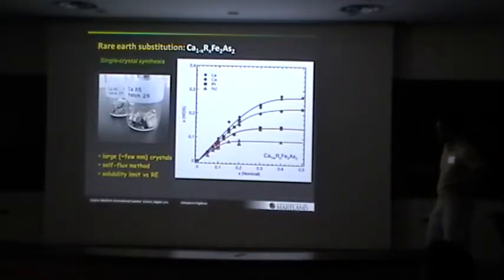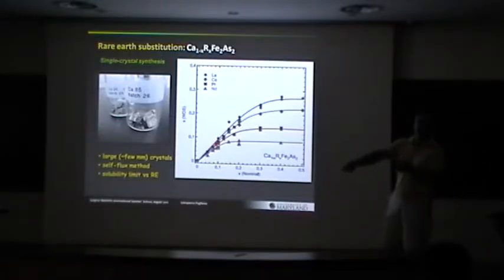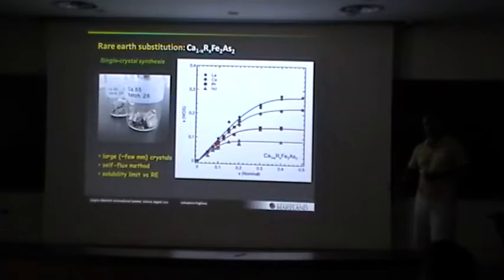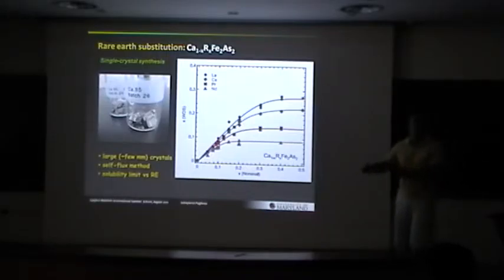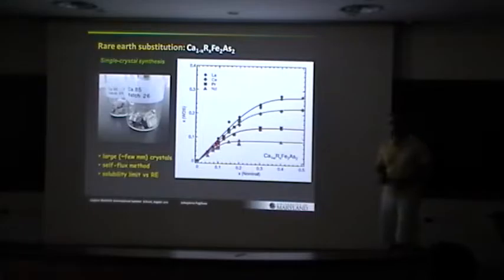This is the concentration of rare earth we start with, and this is what we measure. You can see that for lanthanum, for instance, we get a pretty good linear relationship up to some higher concentration, and we kind of run out of steam, so you can't put more lanthanum in. And then as we make the rare earth smaller, we can put less and less. So by the time we get to neodymium, we can only put in less than 10%. And the more we try to put in, it just doesn't fit, at least with just this ambient pressure growth.